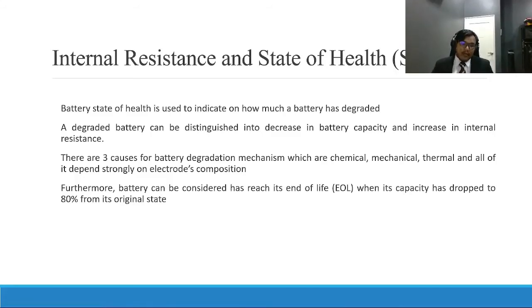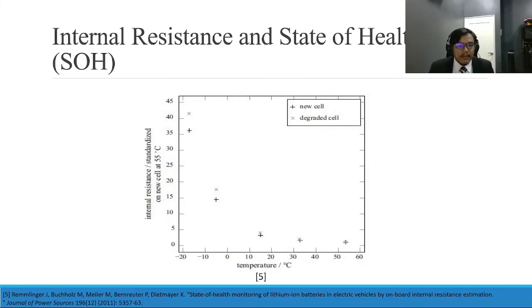So like I said before, using a battery at high temperature can have an advantage, which is low internal resistance, but also a downside, which leads to faster degradation. And this graph was conducted by Remmlinger in 2011. So you can see the comparison between a new cell and a degraded cell. A degraded cell has higher internal resistance.